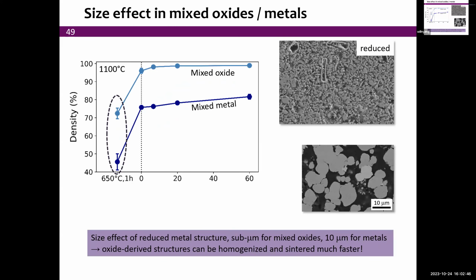And we see that as we go to a higher temperature, the size effect becomes really important. So the mixed oxide reduced, shown here, is much, much finer than the mixed metal, for which we have much larger particles. So this is really the effect of having much finer particles that gives you almost 100%, because we create them from scratch, so to speak, from oxide. Whereas if you start from pre-alloyed powders, or even just pre-fabricated powders, we are plateauing at about 80%. So this is going to be pretty weak compared to that. So that size effect is shown here.